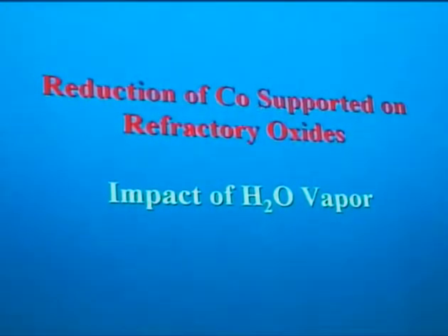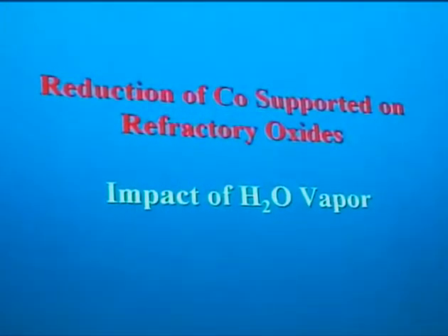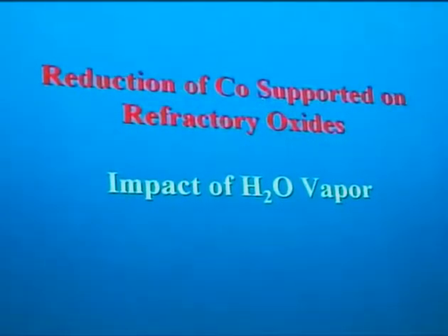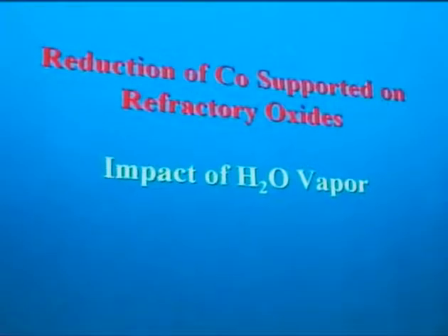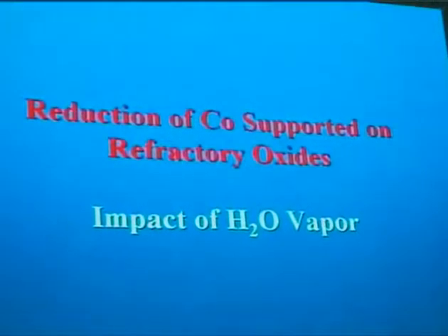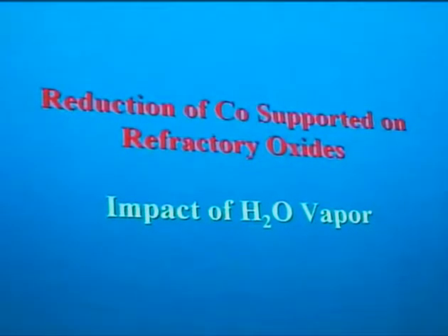It's well known, going back even before the 60s and 70s, from a lot of work in Holland on nickel on silica and formation of nickel silicates. Certainly this is a base metal, and of course it can react with refractory oxides. And the key element to making that happen is the water vapor.